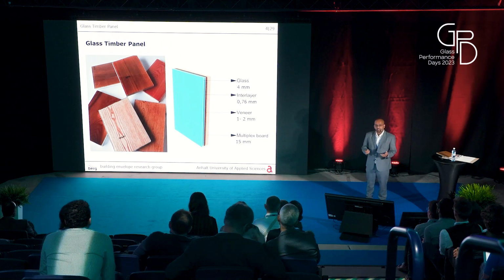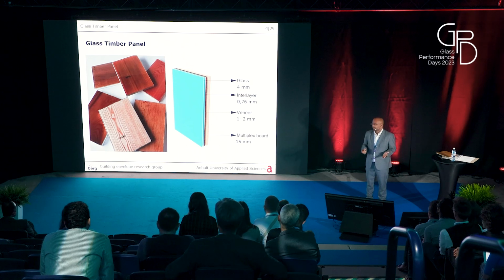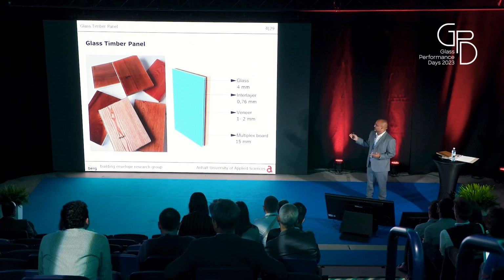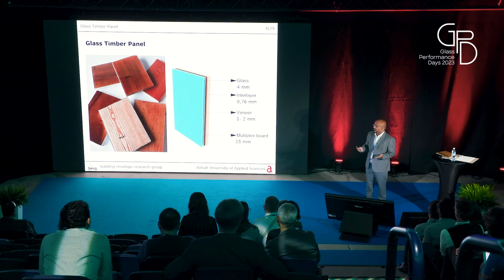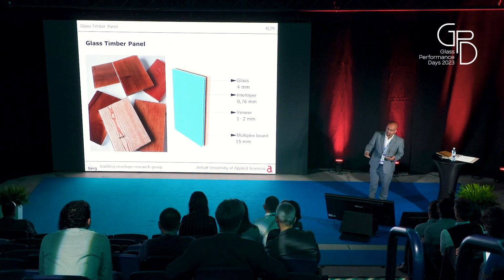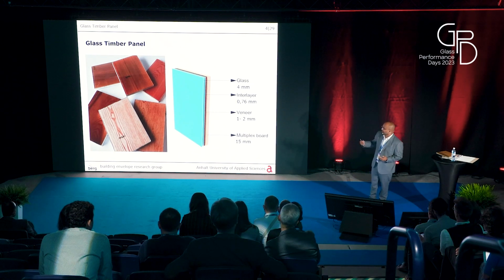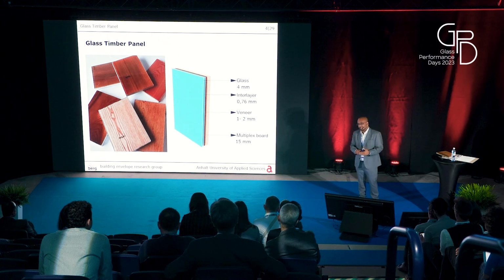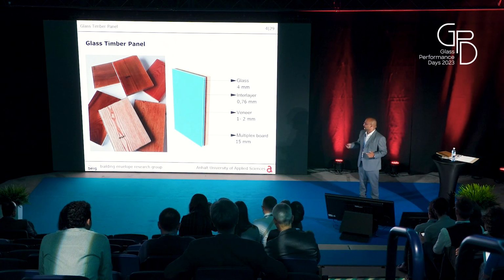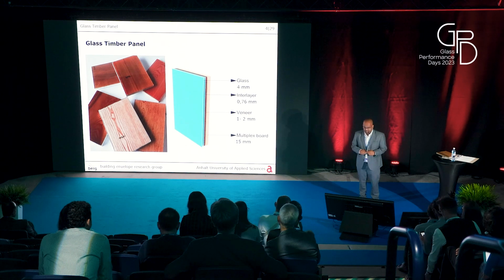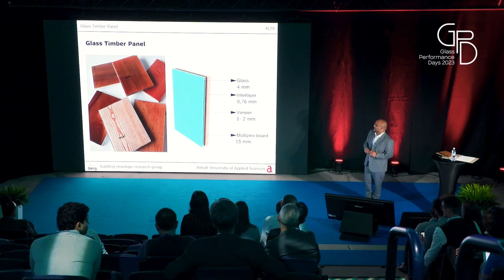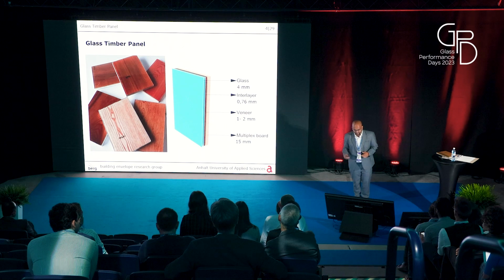The lamination process is similar to the lamination of glass. Instead of a second glass side, we used the veneer, and it is packed in a silicone vacuum bag and heated up to 140 degrees, and it worked quite well. We had some positive results. I'll show you some examples.